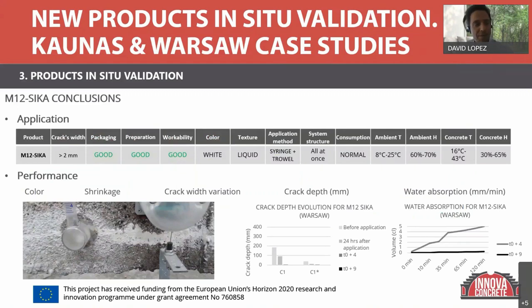Here you have an example with a crack sealant that was developed together with the Instituto Torroja and SIKA. And in terms of application, what do we look at? In this case, it's a crack sealant that was oriented to seal cracks over 2 millimeters and under 5 millimeters. We had to transport this from Spain to Warsaw and Lithuania, and then for us it's important also to see if it has a good packaging, if it's easy to transport, and this type of things.